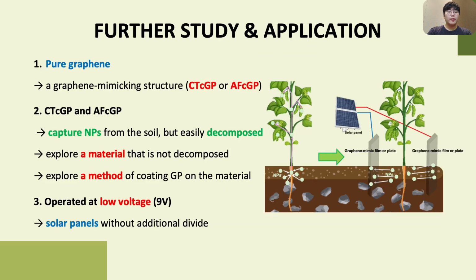Although the graphene mimicking film actively captures nanoplastics in the soil and prevents their penetration into crops, agarose films were degraded by the soil moisture and graphene powder was detected from cellophane tape as time passed. Therefore, exploring moisture-resistant, non-toxic flexible materials and developing a technique to coat them with graphene powder could enable long-term use and provide a sustainable solution without additional cost.